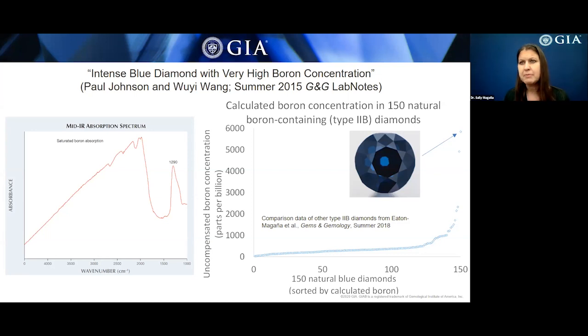On the right, I show a chart that plots the determined boron concentration for 150 natural blue diamonds that were calculated as part of our 2018 article on blue diamonds. You can see that the vast majority of natural type 2B diamonds have boron concentrations less than about 500 parts per billion. And I show this comparison to give an idea of the incredible quantity of boron that we found within this natural diamond. I checked our database, and this diamond is still the record holder for type 2B natural diamonds seen at GIA.